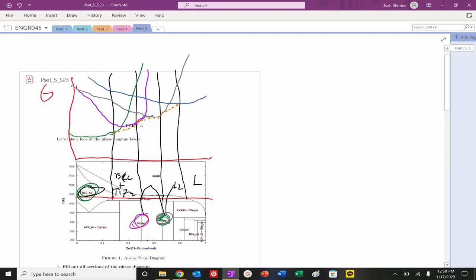So let's examine this. This is a single phase region. This is my lowest energy curve. This is a 2-phase region. Common tangent here and here. Equal chemical potential, because we know that the slope of our Gibbs free energy curve versus mole fraction is approximately our chemical potential. So chemical potential must be equal. Same thing here: a 2-phase region between this phase and this phase. We're good to go. A 2-phase region here between this phase and this phase. Common tangent. The slope is equal here, to the gray and here in the blue.